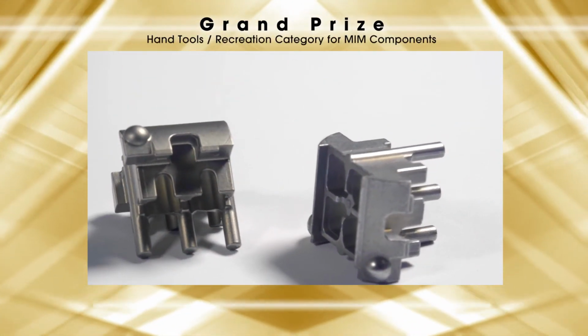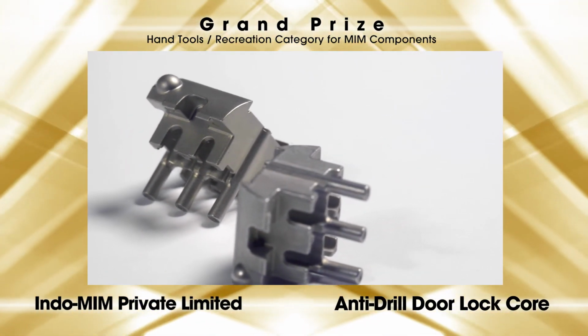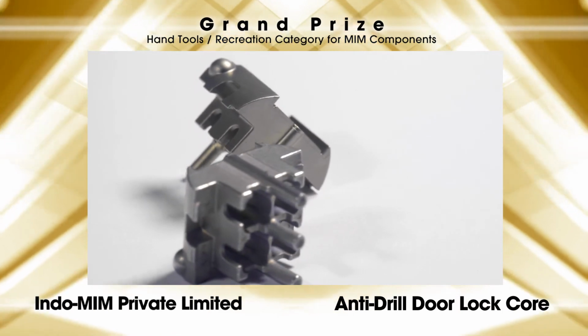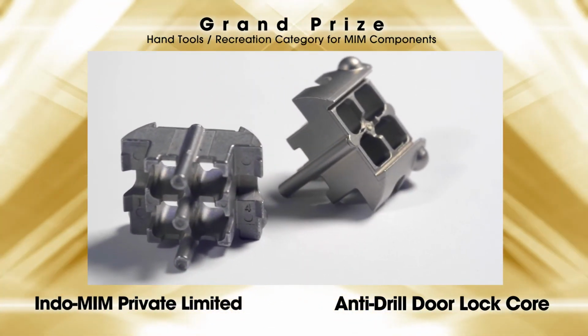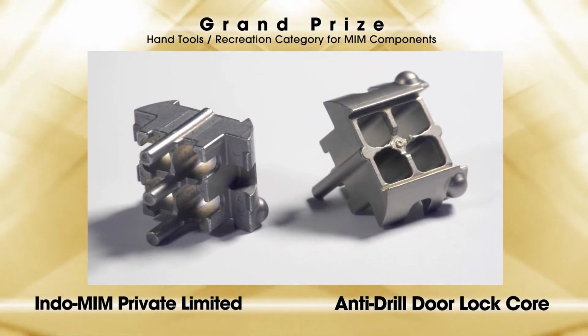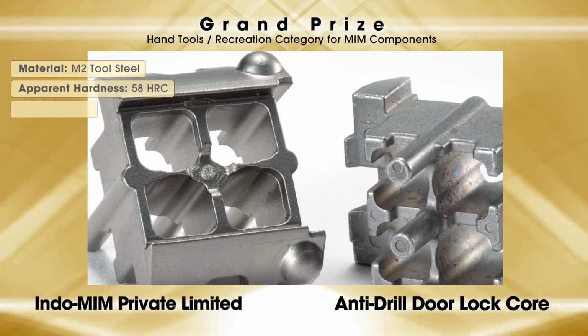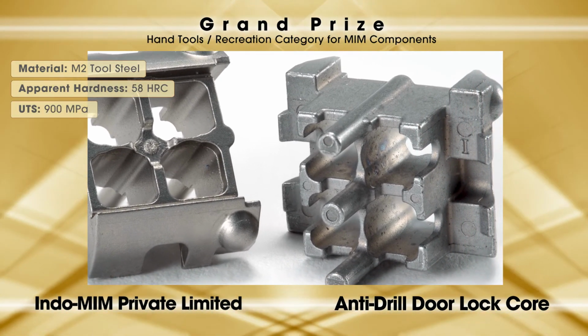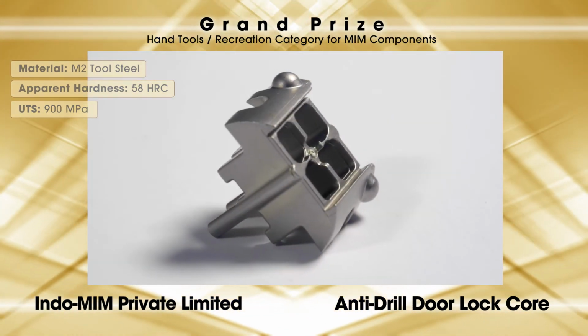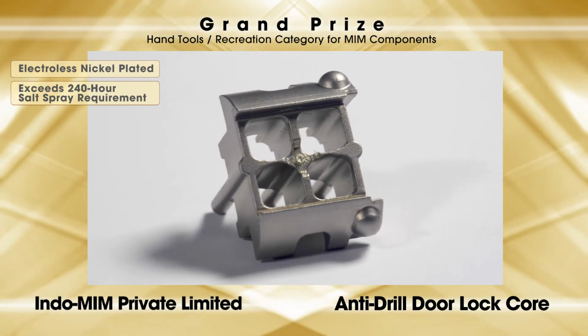Indo-MIM Private Limited received a grand prize in the Hand Tools Recreation category for MIM components for an anti-drill door lock core. This quick-change anti-drill door lock core is used in a high-security door lock assembly. The component requires high strength and good wear resistance. It is made from M2 tool steel, heat-treated to an apparent hardness of 58 HRC with a tensile strength of 900 megapascals. The parts are electroless nickel-plated and can withstand 240 hours in a salt spray test.